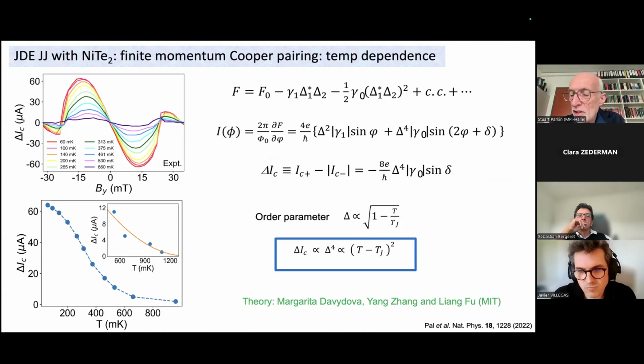As I mentioned earlier, we have these topological surface states. What does that mean? That means, as I mentioned, that through the Rashba effect, the momentum of the electron is coupled to its spin, or its spin is coupled to the momentum. So when we apply a field perpendicular to the momentum, the flow of the electrons, that leads to a spin splitting of these spin polarized surface states. And so that means now we have an exchange splitting. And due to that, just for the reasons I discussed earlier, the Cooper pairs are now formed from electrons which have distinct momenta, and this then leads to basically a finite momentum Cooper pairing effect.